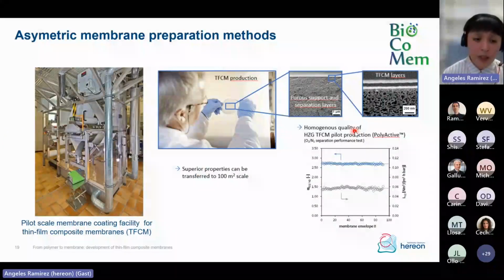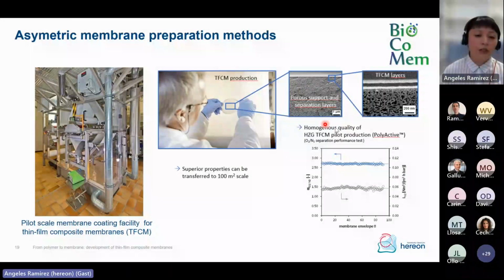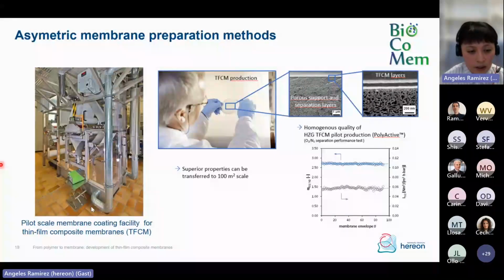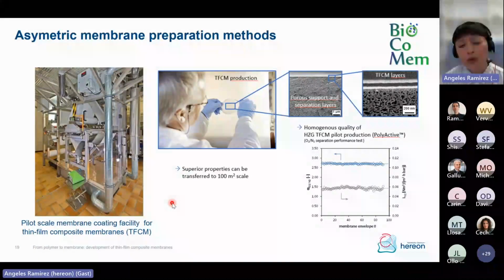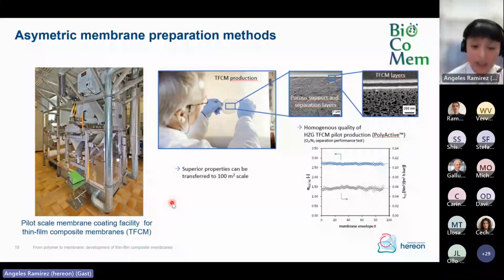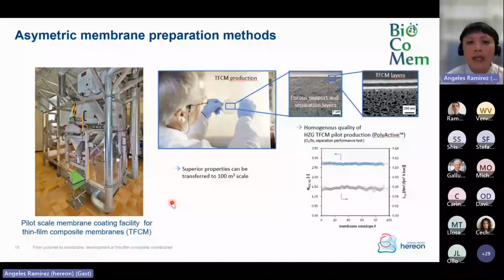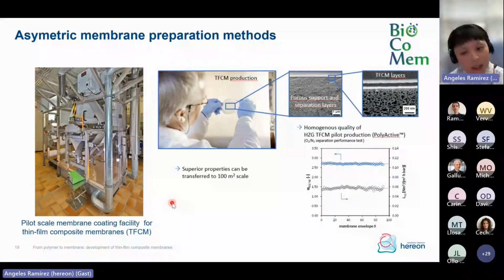Now, as I mentioned, this coating procedure is modified meniscus coating. We do it here in this pilot scale membrane coating facility at our institute, which allows us to prepare membranes with lengths of up to 250 meters and widths of around 60 centimeters. And during membrane preparation, we ensure the quality control by taking samples at regular intervals across the membrane batch, and then measuring the oxygen and nitrogen permeances and selectivities.